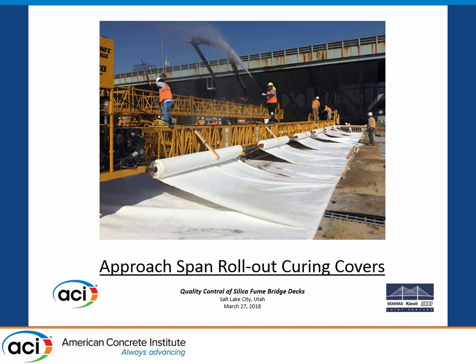Okay, so what they did, they call these the toilet paper rolls. And the plastic side goes up, it's got pinholes, and that's the soft side. That's the natural cellulose fibers. And what he does is he wets them before they go down. And then, if you're not satisfied with that, you can put more water on top of them. The pinholes will suck them down.